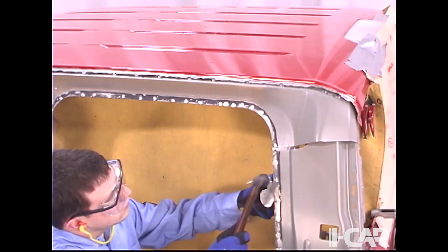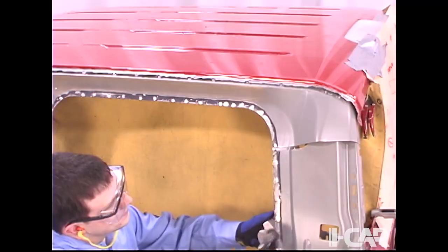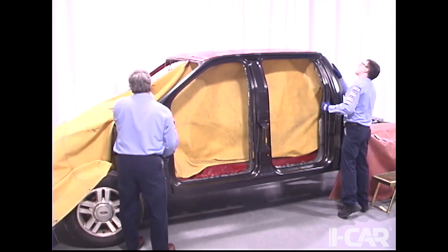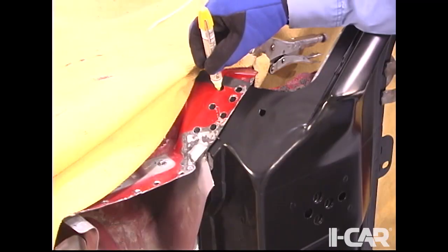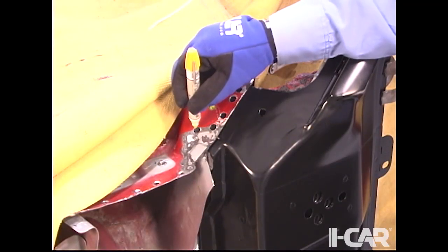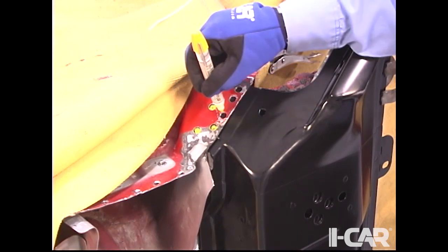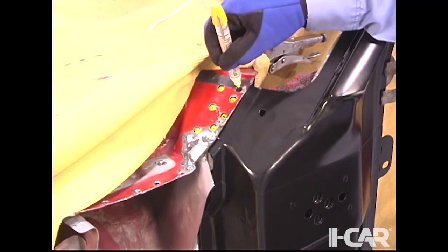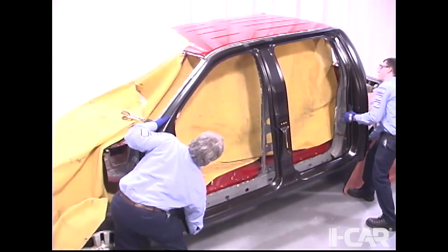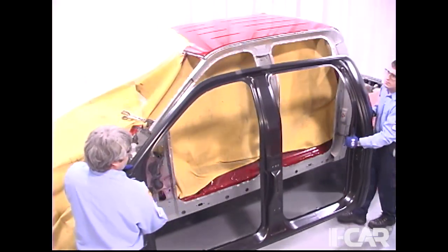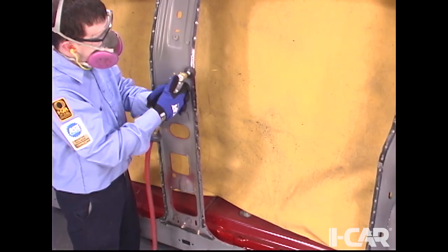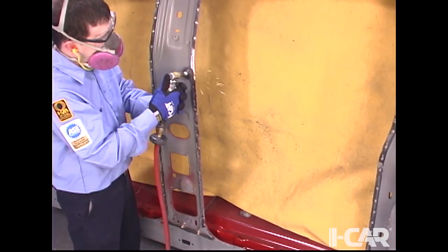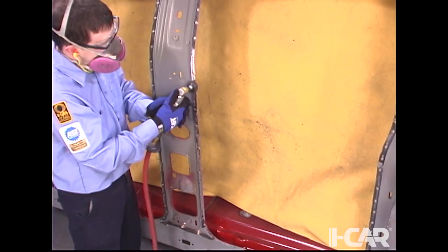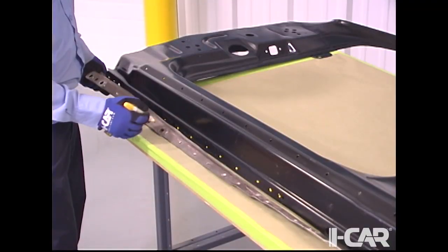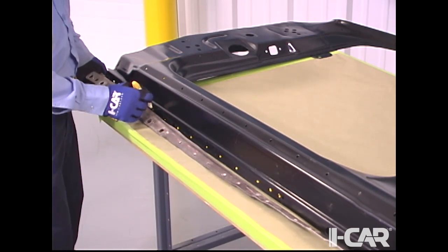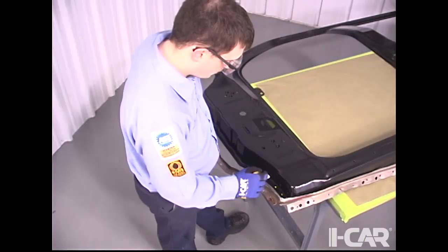After the original panel has been removed and the mating flanges have been straightened, and the replacement part has been temporarily installed to verify proper fit, plug weld locations are marked in areas that are not accessible for the spot welding arms. This is because adhesive should not be applied in the zone of the GMA MIG weld. After the plug weld locations have been marked, the panel is removed and all of the coatings are removed from the mating flange. The bulletins for both bonding procedures require the removal of the galvanizing on the mating flanges. Though Ford recommends using spot welds, some areas are inaccessible, so GMA MIG weld bonding is used.